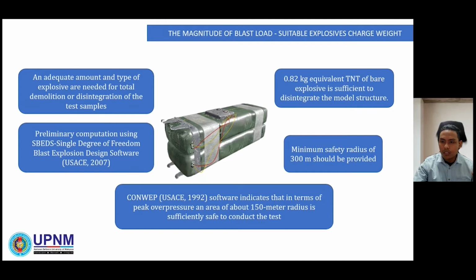Preliminary computation using SBEDS, the single degree of freedom blast effects design software, indicates that 0.82 kg equivalent TNT of bare explosive is sufficient to disintegrate the model structure. However, the software does not detail the level of failure that could happen. The failure mode was based on the rotation angle and ductility response.